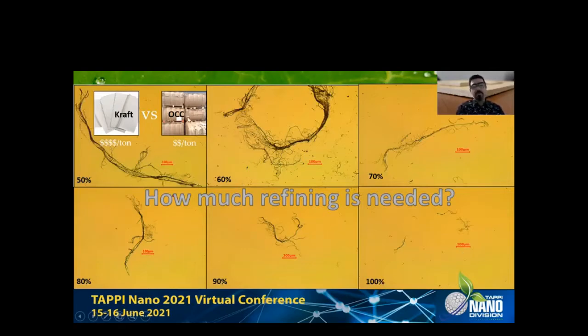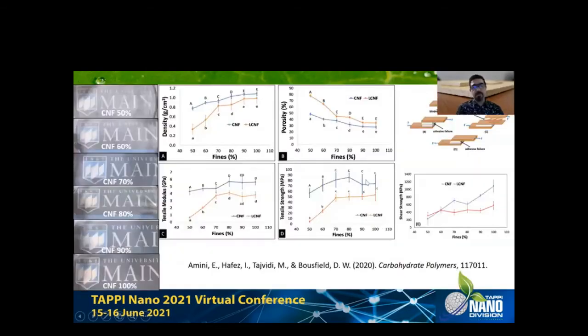And also, there is another way to reduce the cost of nanocellulose, which is to go from bleached kraft pulp to something like OCC fiber, which is much cheaper. So we did the same thing. We produced CNF from bleached kraft pulp and LCNF, lignin-containing nanocellulose, from unbleached kraft pulp. We checked their density of the films and the tensile modulus and tensile strength of the films. What we saw was that in many cases, the properties kind of level up at around 70 to 80% fines content.